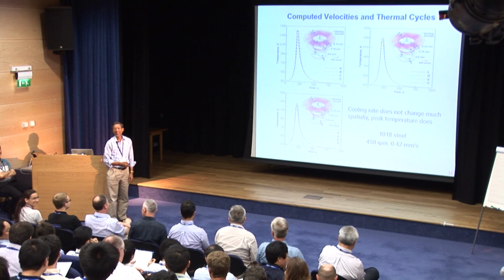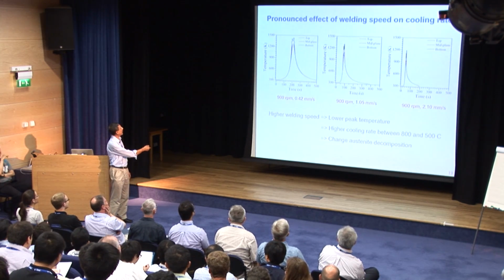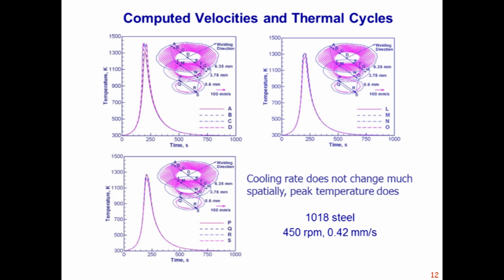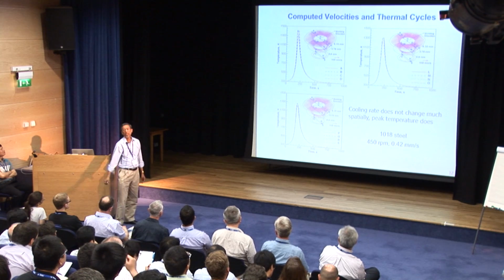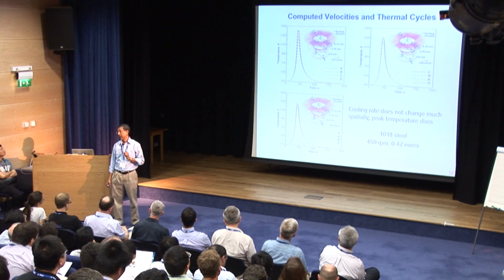Wonderful. I didn't know that it was so popular a lecture, but here we have thermal cycles for the condition that we are going to be looking at the microstructure. Mild steel parameters are here, and we are looking at temperature cycles on the top plane, in the middle plane, and at the bottom plane. And the point here is the cooling rates do not vary all that much, but the temperature at the bottom plane can be about 180 degrees lower than the temperature at the top plane. So in some cases, you may not even form austenite. That's the issue. The cooling rates would not vary a great deal. They will vary, but they will not vary a great deal.